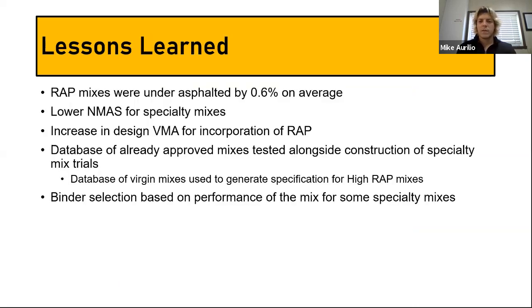So there's a few lessons I think that they learned early on while they were doing some of these specialty mixes. These mixes were kind of designed as experiments to make sure that what they were learning from their evaluation of virgin mixes could be applied properly to future pavements. So the first thing is they learned that their RAP mixes were under asphalted by about 0.6% on average. I think Louisiana did something similar, and I think they found it was 0.7%. So part of the problem with their RAP mixes was they weren't getting enough asphalt cement content.